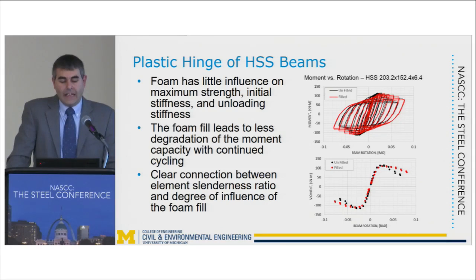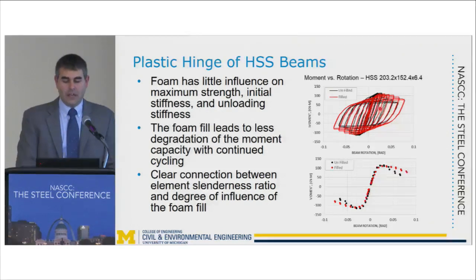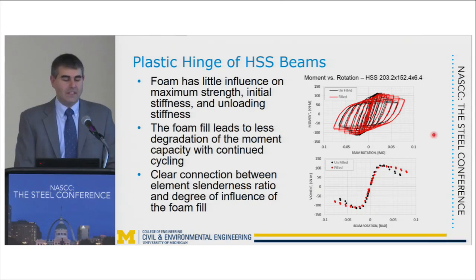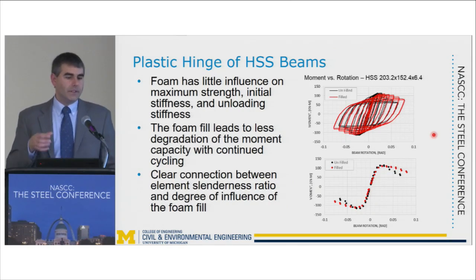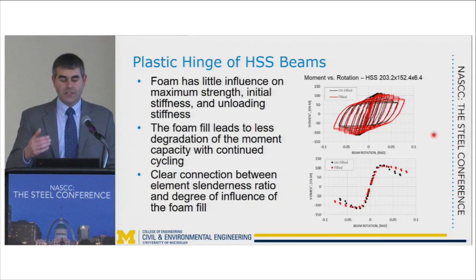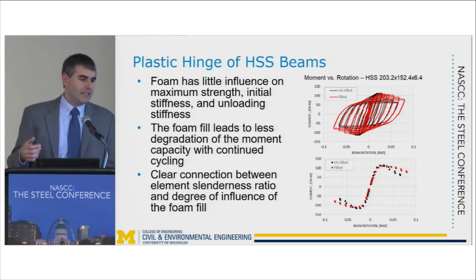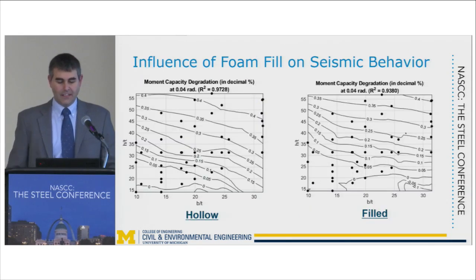Like I said, we're also looking at using it in the plastic hinge of HSS beams. And you can see from the plot here where the black is an unfilled beam that's being cycled and the red is a filled beam that's being cycled. What we see is the presence of the foam fill in that area tends to reduce the amount of moment degradation that we see with continued cycling, which is important because remember, for our special moment resisting frame, we have to be able to maintain 80% of our plastic moment capacity out to 0.04 radians.